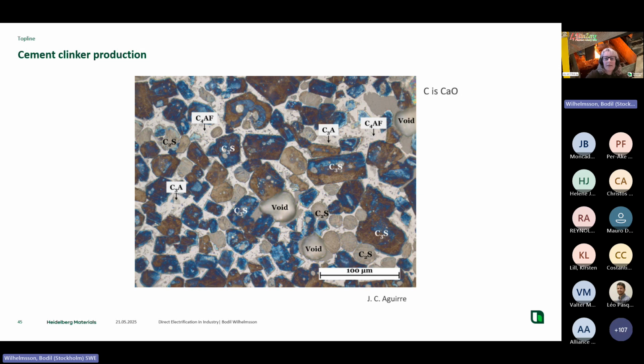And C is here in CaO, quite a different way in chemistry for cement clinker chemistry. And where do we get all the Ca? Yeah, we get it from calcium carbonate. About 80% of the raw material we have in cement production is from calcium carbonate. And to achieve this structure, we need to have the material at a high temperature, approximately 1500 degrees.